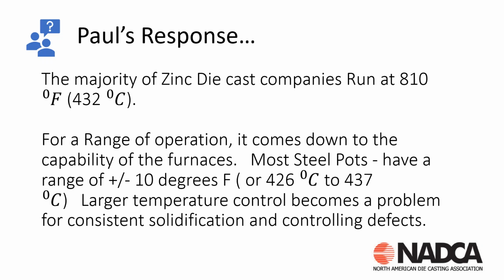So whether it's zinc or aluminum or magnesium, we want consistent furnace temperatures to give us a consistent process during the injection phase of our process. So the range of operation is going to come down to what type of furnace you're using, how good are your furnace controls, what condition your pot's in. All of those conditions are going to tell us what range we're going to operate in. We want to operate in less than plus or minus 10 degrees is what we want.